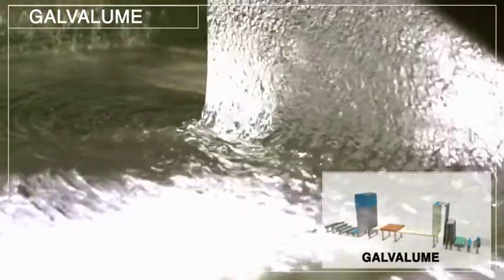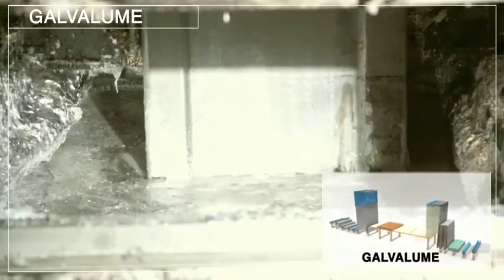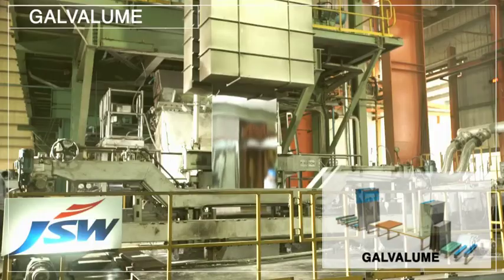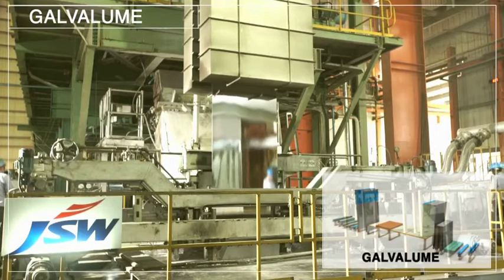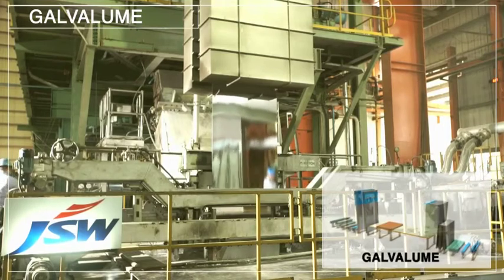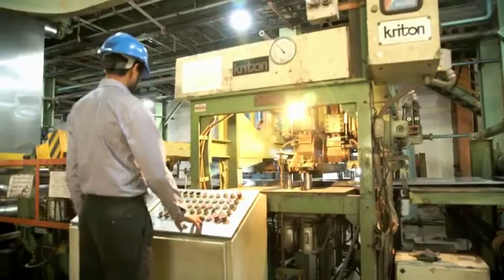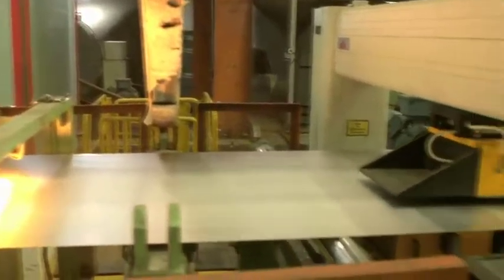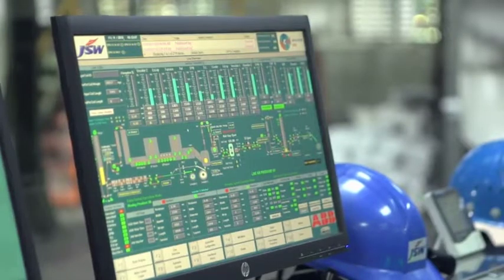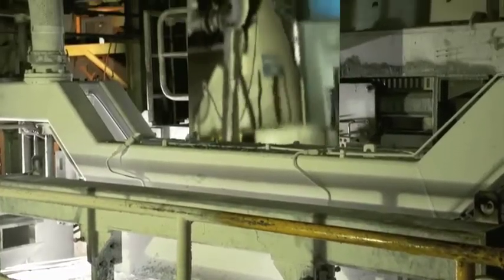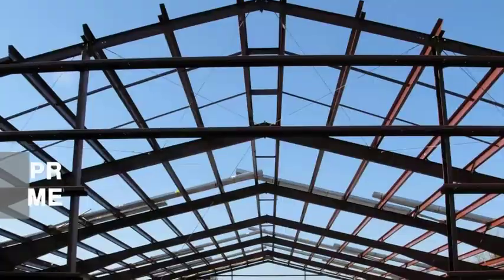Combining the galvanic corrosion resistance of zinc with the barrier corrosion resistance of aluminium, the coating's unique microstructure embeds zinc-rich areas within an aluminium-rich matrix. This allows zinc to provide galvanic protection while restricting its dissolution. This gives a cost-effective steel product for roofing and construction, along with long-term performance against rupture, perforation or structural failure. The surface finish is consistent with uniform spangles.